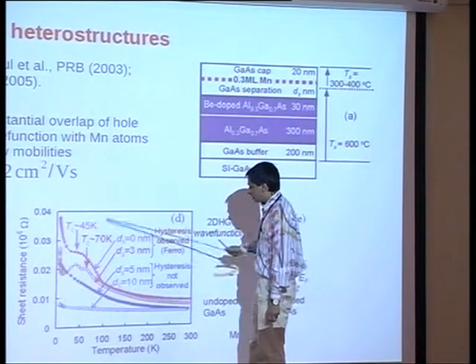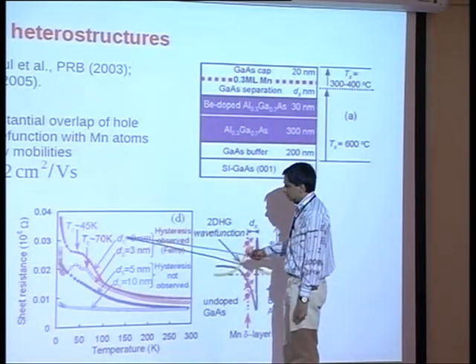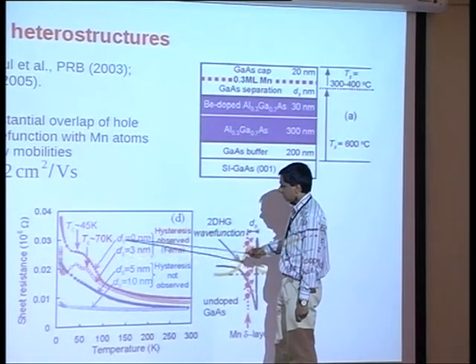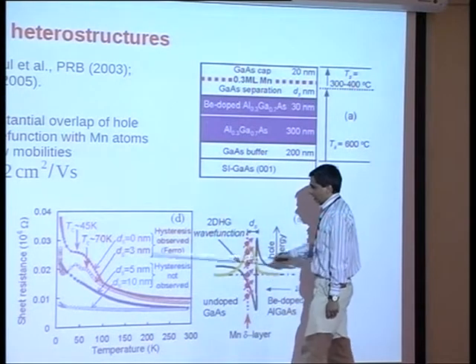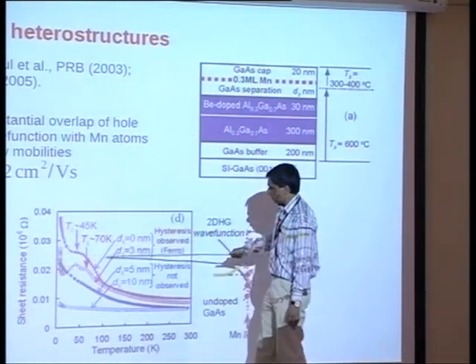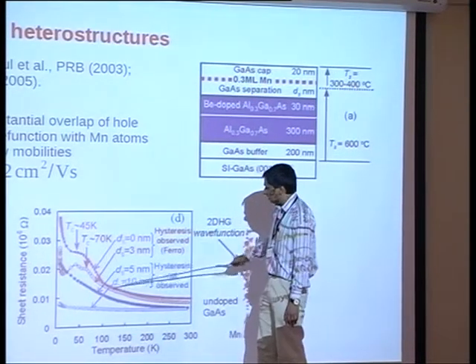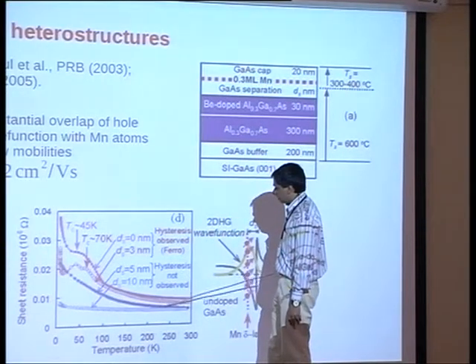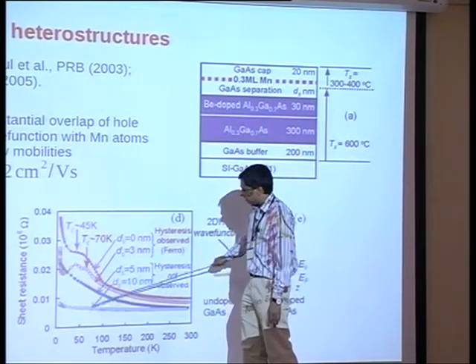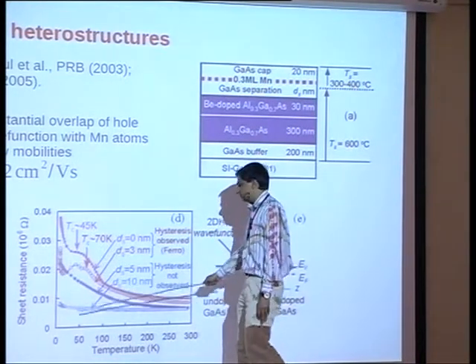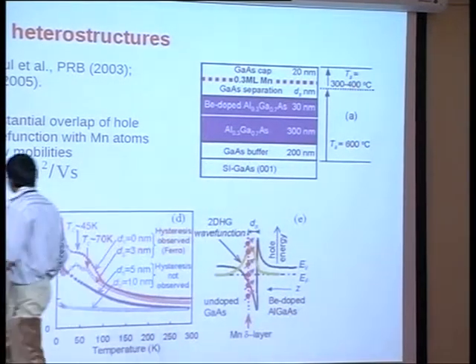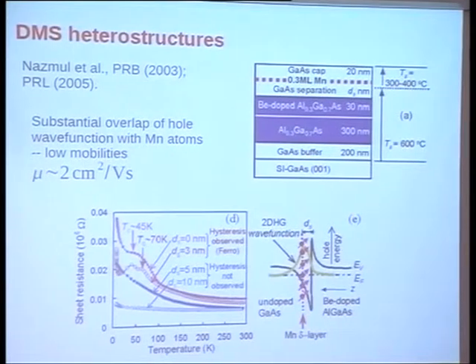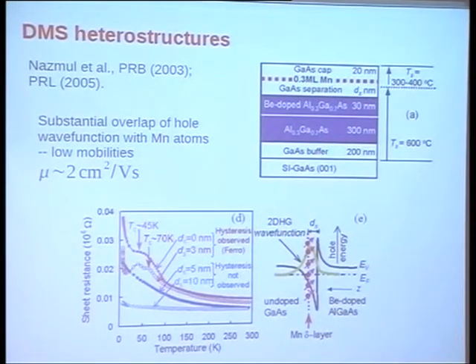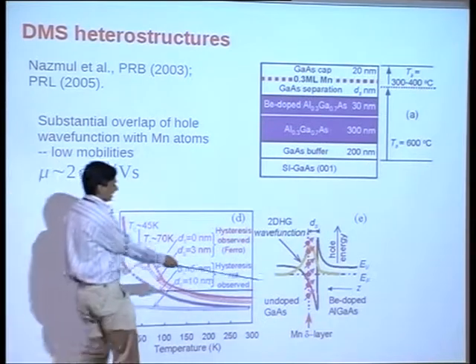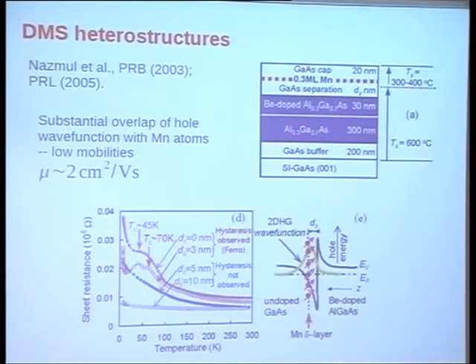But here the plot I have selected is how resistivity looks as a function of distance of this interface from the manganese doping layer. When the manganese doping layer is very close to the interface, you have these pronounced anomalies in the resistivity. And when the manganese layer is very far off, you lose these features, indicating that these may have something to do with ferromagnetism induced by the manganese. Unfortunately, it forms on this side, and it gives very low mobilities.